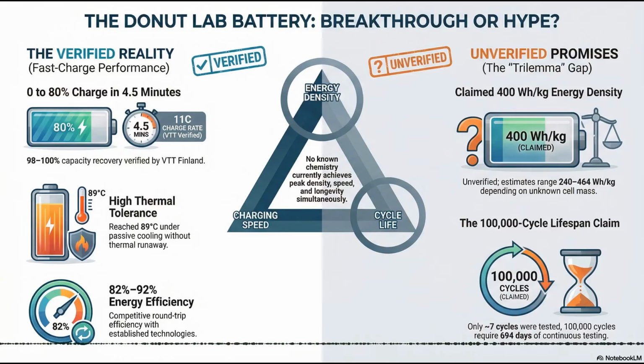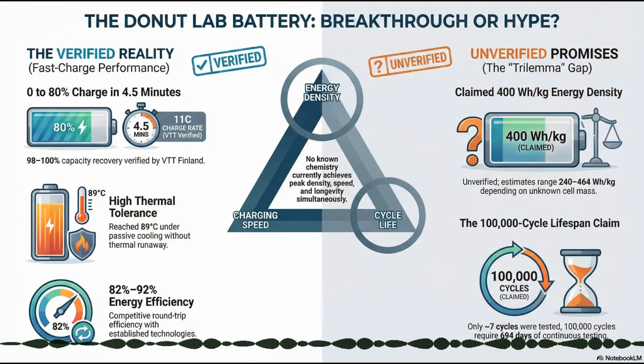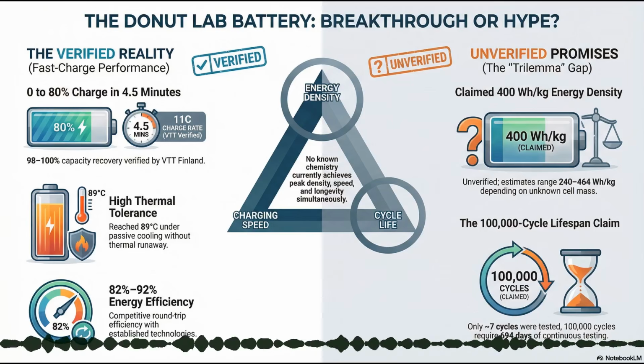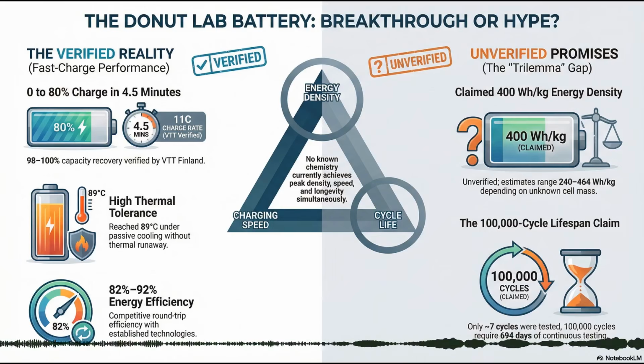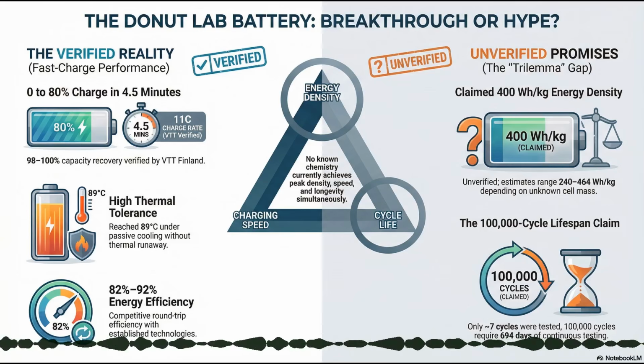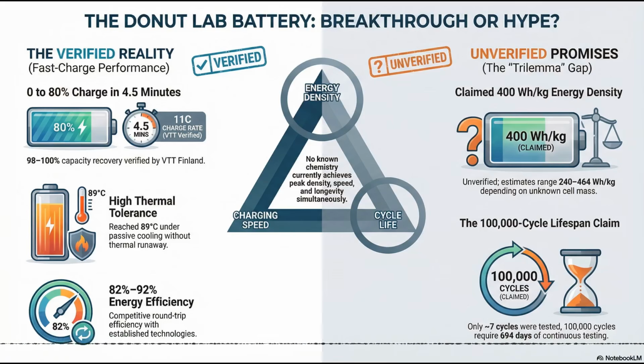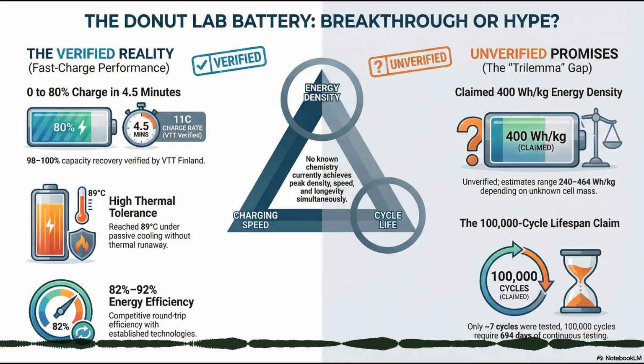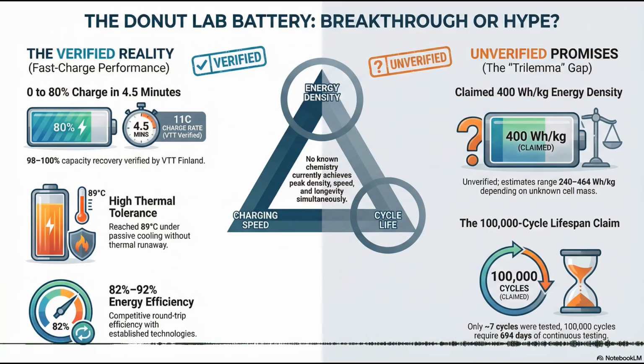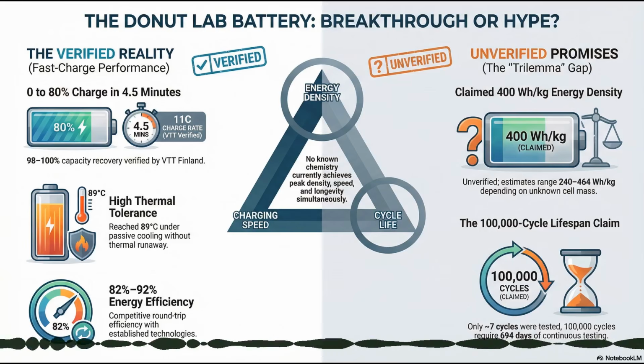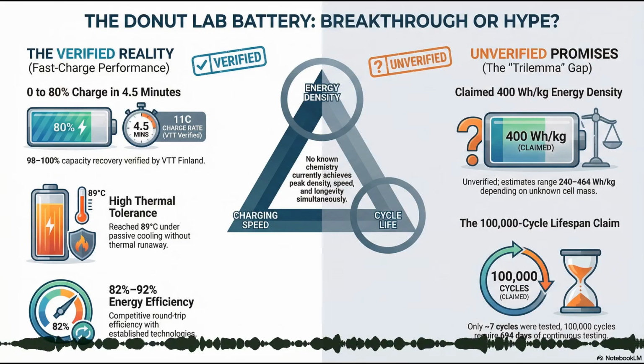Right, 7. And here's where we run into what the engineering community is calling the 694-day problem. Do the math for us. Why is this physically impossible to have actually tested? Even if you could charge the cell in 5 minutes and discharge it in 5 minutes, which is an incredibly aggressive 12C continuous profile and assumes absolutely zero rest time for thermal equalization, a single full cycle takes 10 minutes. Okay, 10 minutes per cycle. 100,000 cycles times 10 minutes is 1,000,000 minutes. That is roughly 694 days, almost 2 full years of nonstop, 24/7 cycling.